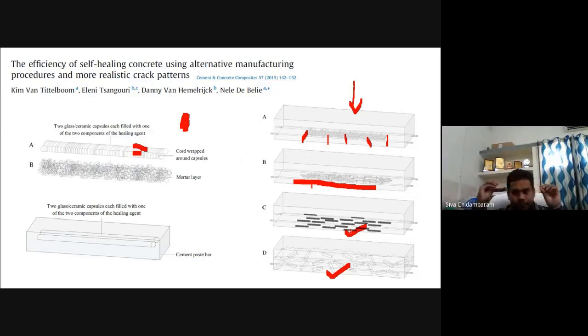These capsules have adhesive chemicals inside them. So what will happen when a beam is trying to crack? The capsules will break. The capsule is a brittle material, so the capsules will break. When the capsules break, the hardener and primer will leak gradually, in small amounts, coming down because of the gravitational force. When the two parts, hardener and primer, combine with each other, they will try to penetrate through the cracked surface. Because it's a very fine crack, the penetration will be very gradual. When they meet together, it will get set.